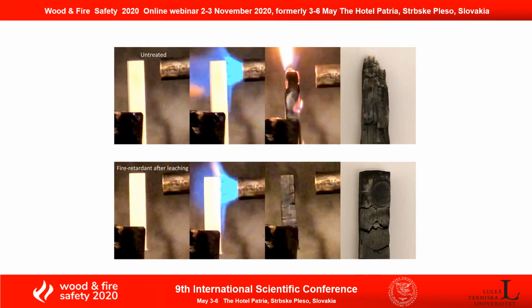And here shows the screening test of the untreated wood and the treated wood after leaching. To perform this screening test, I applied a burner with approximately 2000 degrees Celsius against the material for around 1 minute. And as you can see, for the untreated material, after you remove the heat source, the material continues burning, and on the other hand, for the treated material, after you remove the heat source, it stopped burning, and the treated wood remains in its original structure.